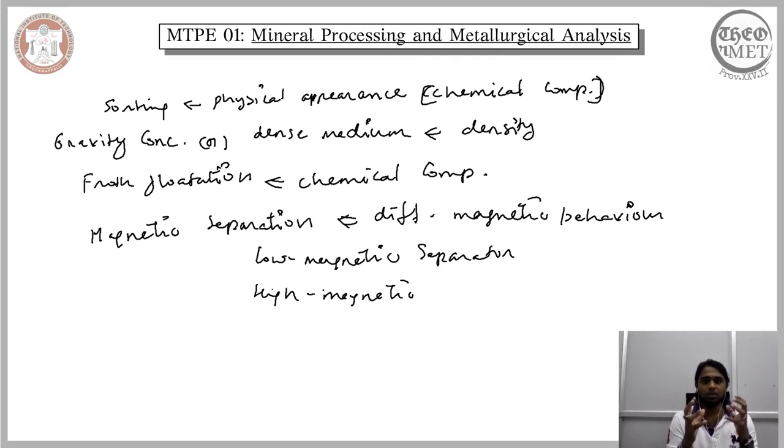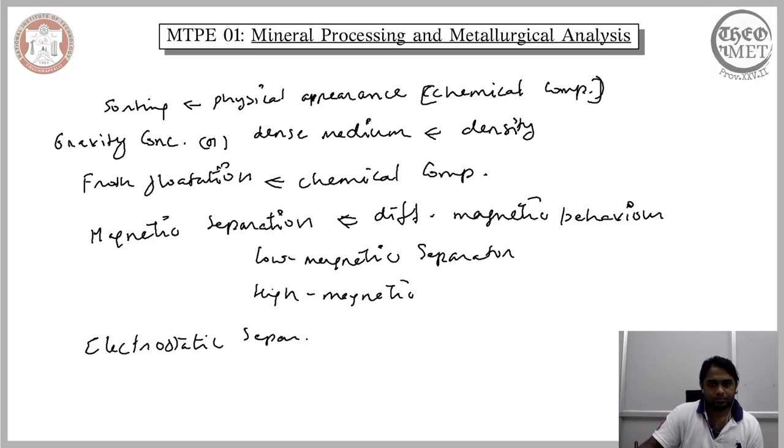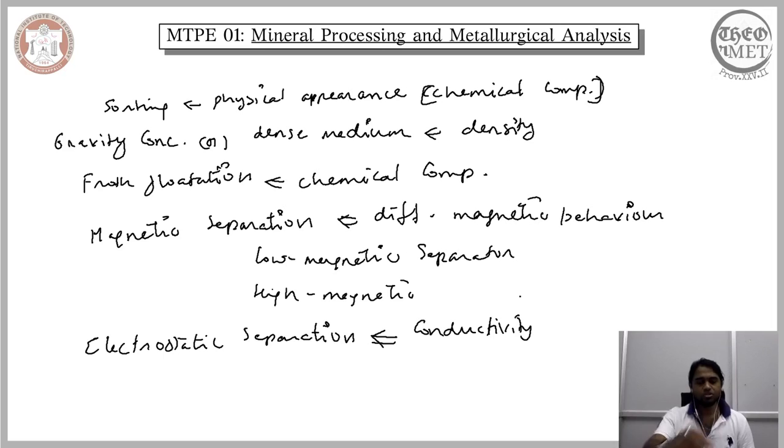Now, the final technique among these wide categories of techniques involved in concentration is referred to as electrostatic separation. Electrostatic separation makes use of the difference in the electrical conductivity of the gangue and the mineral particle. So you have concentrate and gangue, and also some middlings, mixed up as it is given to us, a mixture of these different particles. When these different particles exhibit a different degree of conductivity, electrostatic separation can be exploited to separate the concentrate from the rest of the particles.